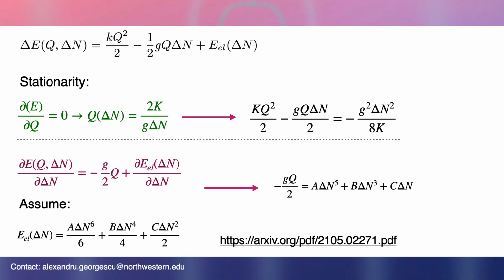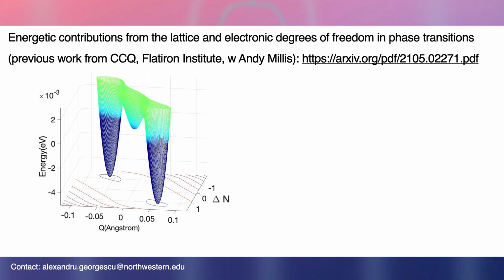In this case, for metal insulator transition compounds, this is the transition to an insulating, symmetry-broken state. We've applied this methodology to the metal-insulator transition compounds described by the formula RNiO3, where R is a rare earth, their heterostructures, and Ca2RuO4, and figured out that one of the main drivers of the transition to an insulating state at low temperature in both of these materials, as well as in their heterostructures and thin films, is the electron-lattice coupling. For more detail, please see our paper.